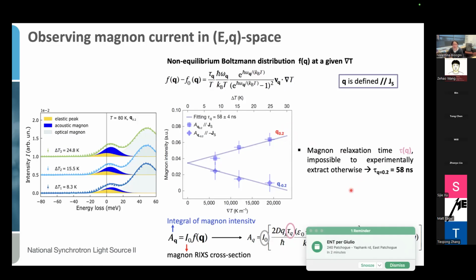And by having access to these parameters, it actually opens the way to calculate all momentum-dependent parameters like heat conductivity and Spin Seebeck conductivity at a fixed Q. And ideally, by performing this measurement as a function of Q, one can then integrate and obtain the macroscopic heat conductivity or spin conductivity for a material without actually using estimated parameters.